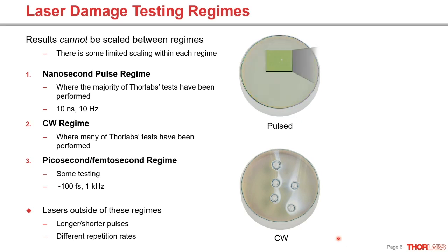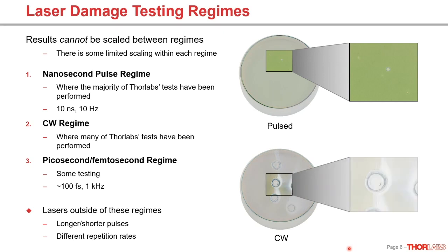And over here on the right, you can see damage from a nanosecond pulse laser, and you can see that that's a relatively fine, relatively uniform circular spot, and that's typically what you're going to see in the pulse regime, whereas in contrast, in the CW regime, you can see this is very much burned and melted into the substrate, and this is an effect of the different mechanisms at work in these two separate regimes, which I'm going to get into in a second.